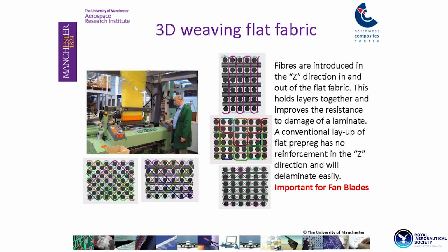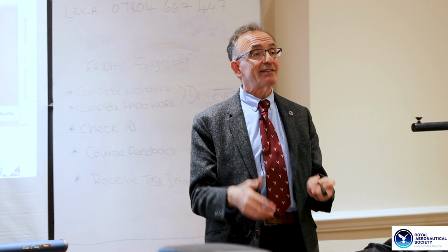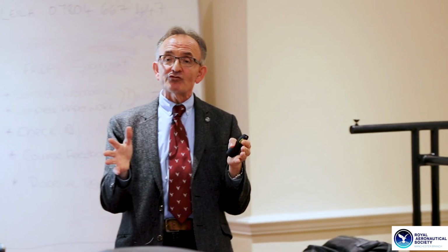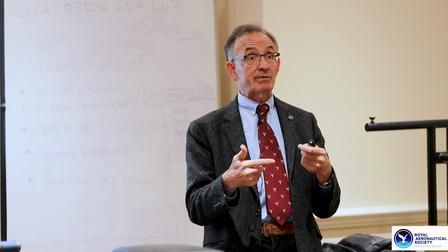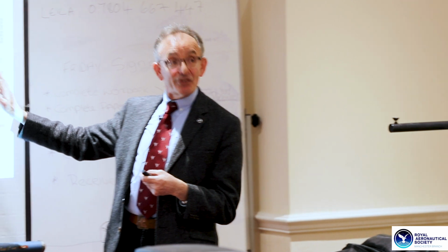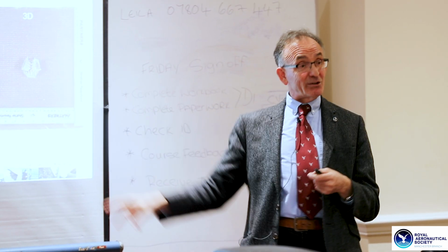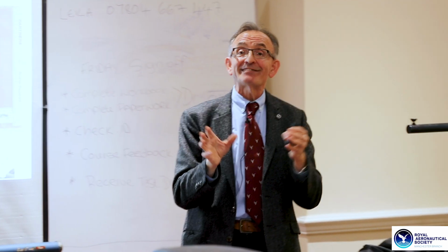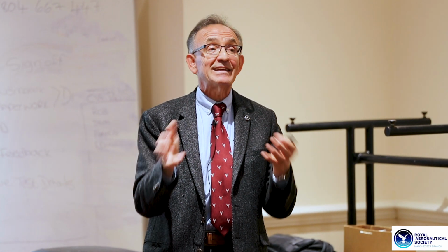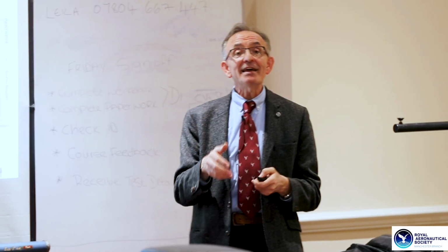Or another way of preventing brittle fractures and brittle failures is by reinforcing our composite through the thickness. So you prevent the composite from delaminating at relatively low applied loads. And the effect of the through thickness reinforcement is visible under an impact event. So on the left-hand side, we have a two-dimensional woven fabric with no through thickness reinforcement. And on the right-hand side, we have a three-dimensional woven loaded under the same impact conditions. But what is missing from here is that we don't get that extensive delamination and extensive matrix cracking.